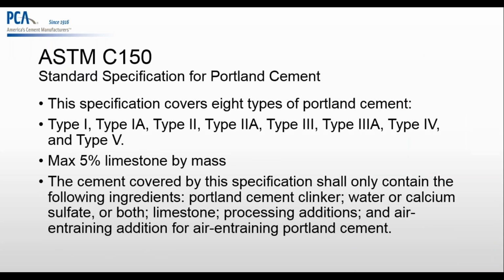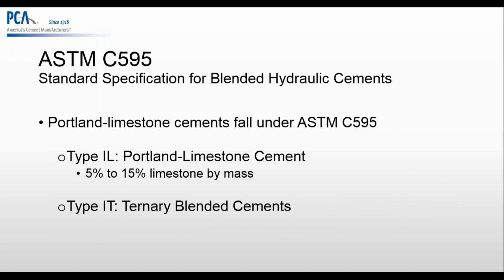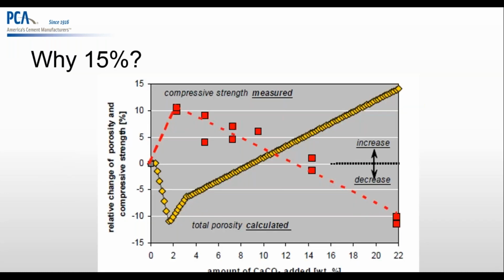Just a quick reminder, with the ASTM C150, the ASTM C150 that all the engineers, the architects, the specifiers know, they always use ASTM C150 in the specs. Well, this specification allows a maximum of 5% limestone already in the cement, right? But its cousin, the ASTM C595, this is where we have to tell the specifiers to include the ASTM C595 in the project specs in order to use the Portland limestone cement, right? The type 1L. Like Justin said, the Portland limestone cement allows a ground limestone from 5 to 15% by mass. So how does limestone work exactly?